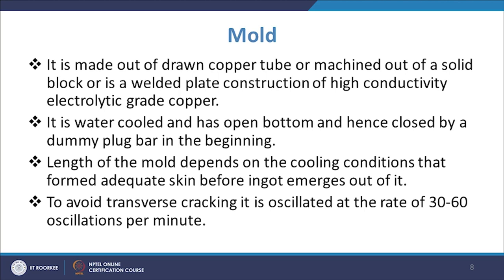But then, as we discussed, since the melting temperature of copper is smaller as compared to that of steel, we need to have another cooling mechanism constantly so that it can take the heat away quickly and it should not melt also, and for that it is normally water cooled and has open bottom and hence closed by a dummy plug bar in the beginning. So, initially in the beginning we close it with a dummy plug bar and then normally it will have open bottom and then water will be coming and flowing, and during that process that water will be absorbing the heat which will be released by the liquid metal in the mold.